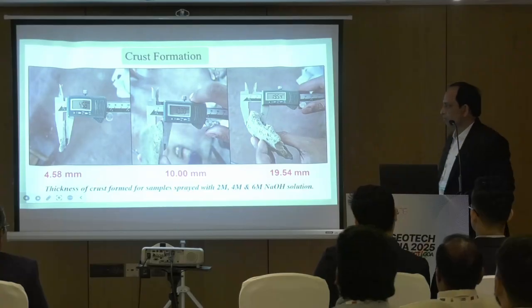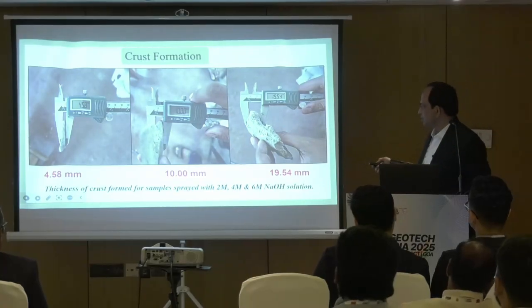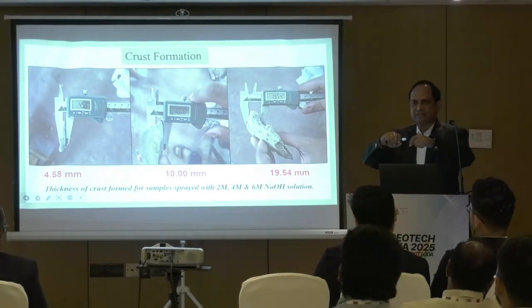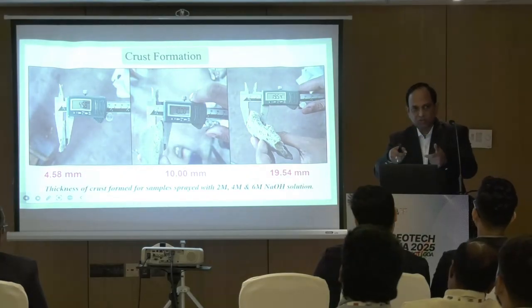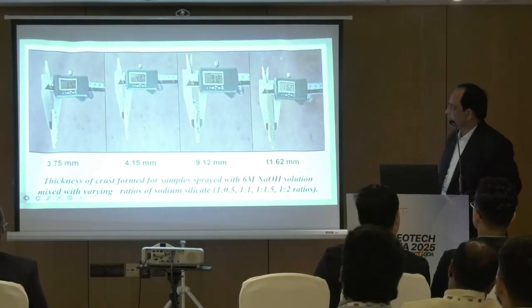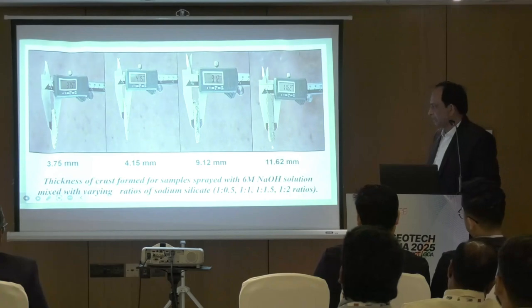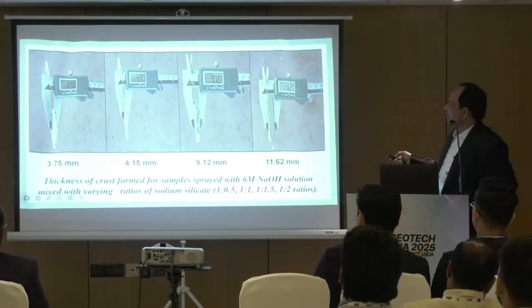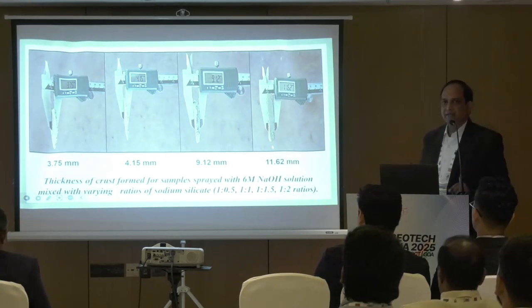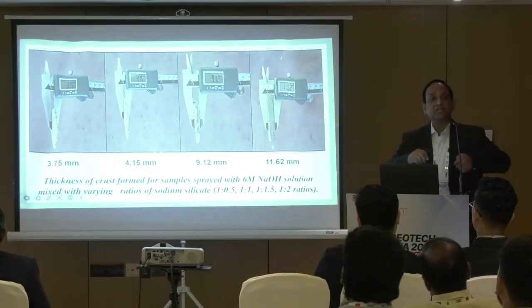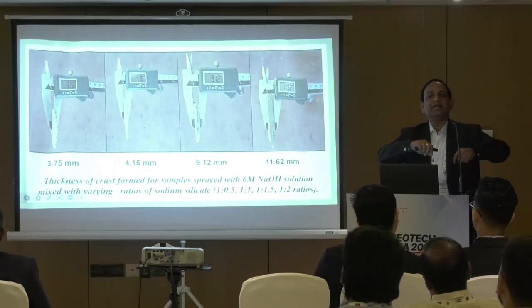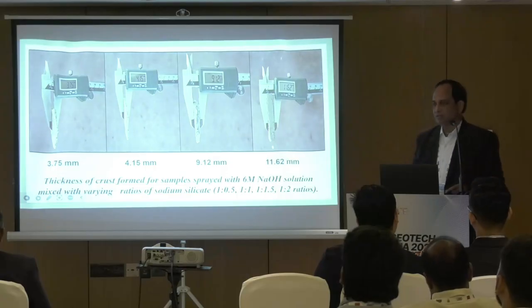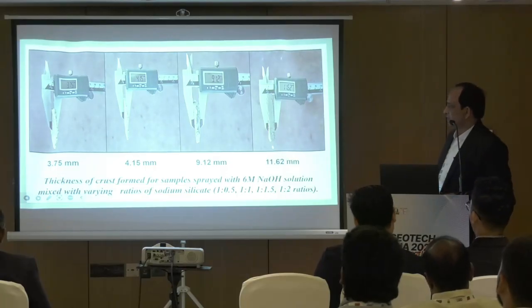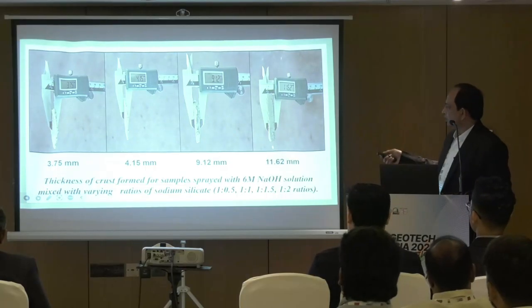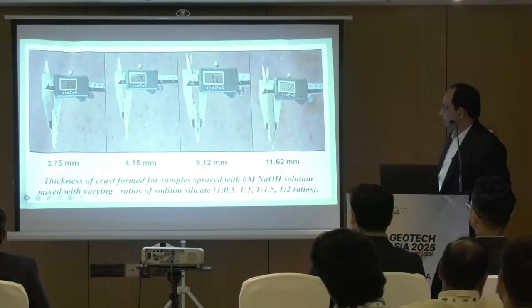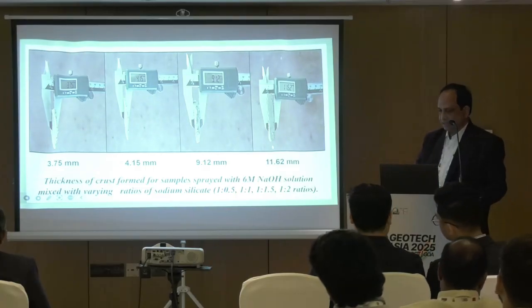Of course, the problem with NaOH is it is a little porous. It is brittle, and we can easily break it. But friends, when we have gone for sodium hydroxide along with sodium silicate, although the thickness is less, it is not that brittle, it's a little strong. You cannot easily break it also. That's the kind of findings we had. Although the thickness is less when compared to only NaOH, this is showing a little higher strength.